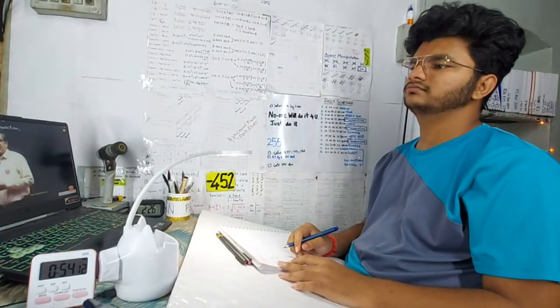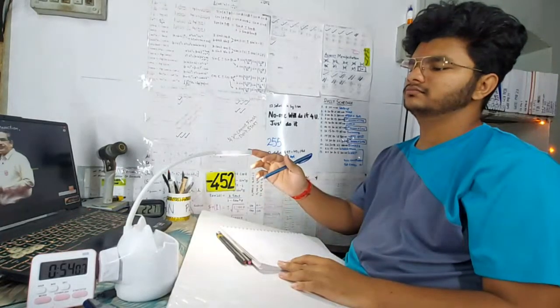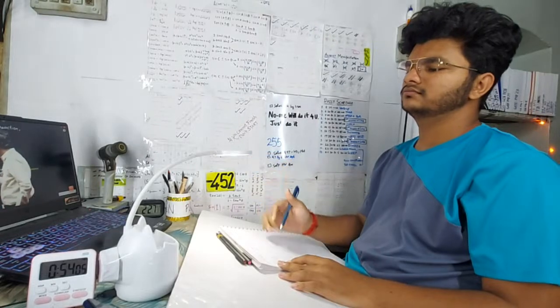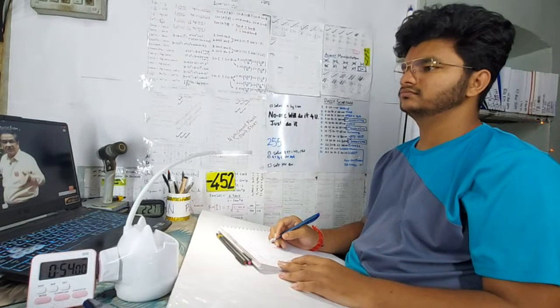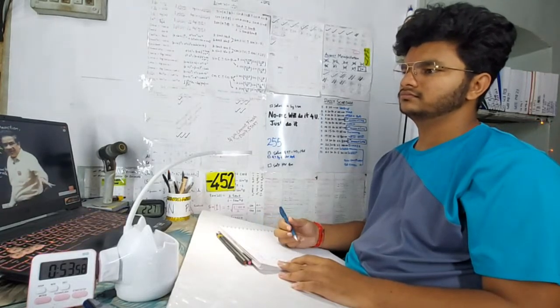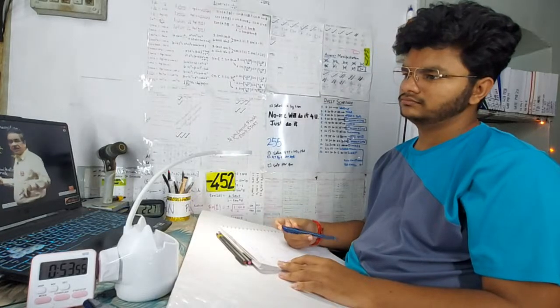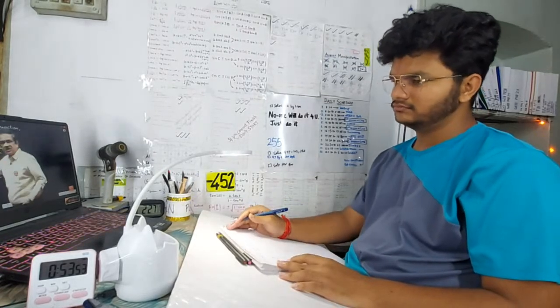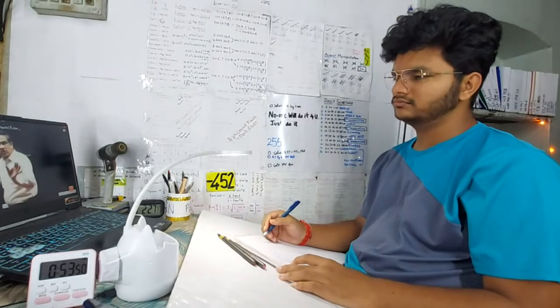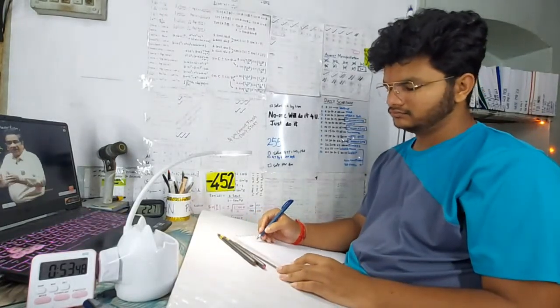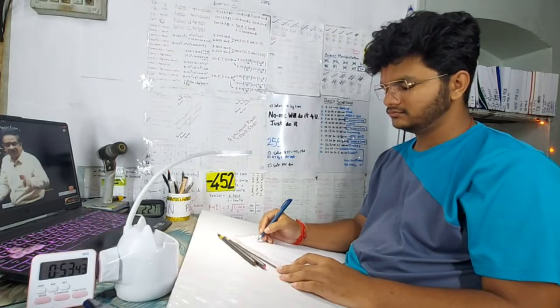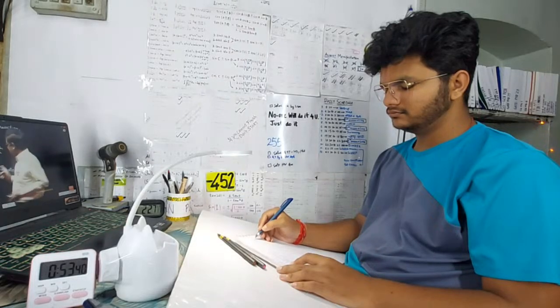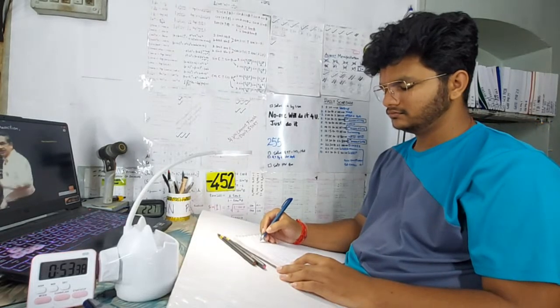Observe, यहाँ से कौन सा जानकारी मिल सकता है हमारे? At lower temperatures, when temperature is decreased, nucleation rate increases. That means the number of nuclei of new phase that are formed will increase. That means at low temperatures, at several places in the material, new phase formation will take place. But at low temperatures, that new phase formed will be associated with small growth rate. At more number of places in the steel, you will find that austenite to pearlite transformation takes place. So nucleation rate is more. But high nucleation rate is associated with low growth rate.